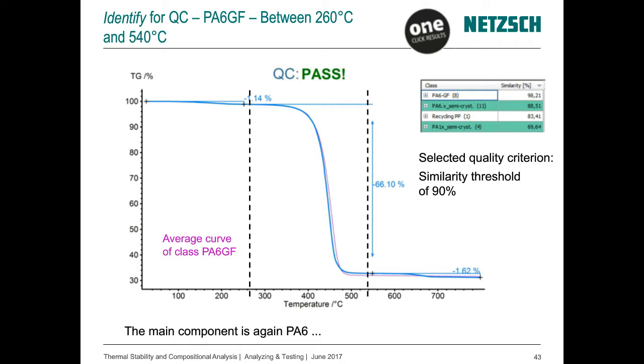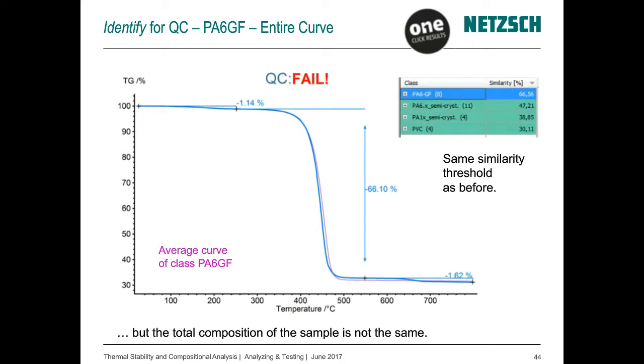But if I don't concentrate on the polymer decomposition, if I use the entire curve and compare it with the class, then we can see that the similarity goes dramatically down. It's much less than 90%. It's about 66%, and this is especially due to the fact that we have an additional small step above 600 degrees C.